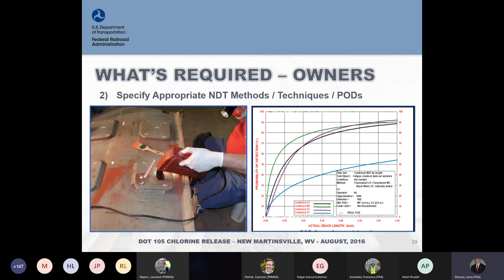So you had industry technicians using industry procedures trying to detect TTCI-generated flaws in locations that were fairly representative of the underframe designs. Here you can see where, in this case, there were some pads welded to the bottom of the tank shell. This particular experiment used both a clamshell design that was open and then fairly covered in certain locations to test people's ability to find the cracks when the location of the area to detect was somewhat obscured.